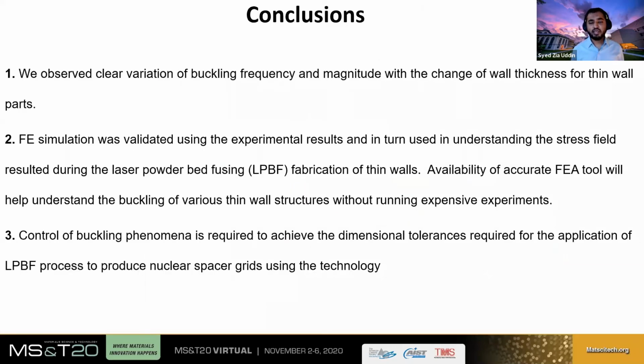So basically, in conclusion, we can say that we have observed a clear variation of buckling frequency and magnitude with wall thicknesses, although this observation was in a very critical and small range of thicknesses: 200 micron, 300 micron, and 500 micron. We've seen many different variations of buckling frequency and magnitude.